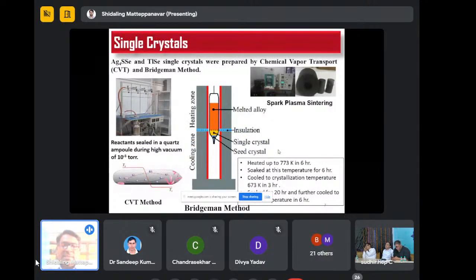Here I am talking about two systems: one is Ag4SSe and the other is Tl-Se. Both systems were prepared with different techniques. Ag4SSe was prepared by the chemical vapor transport method, and the thallium selenide single crystal was prepared by the Bridgman technique. The synthesis conditions are completely different for the two single crystals. This is the single crystal from the Bridgman technique, the thallium selenide single crystal.